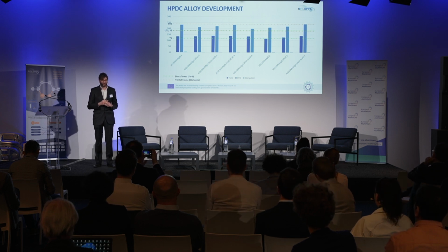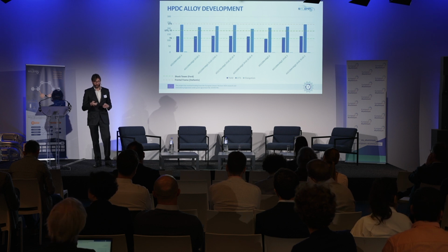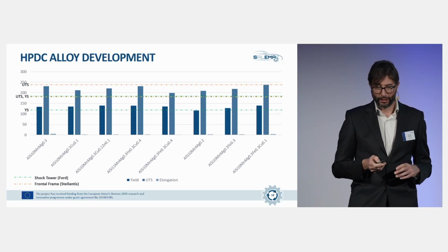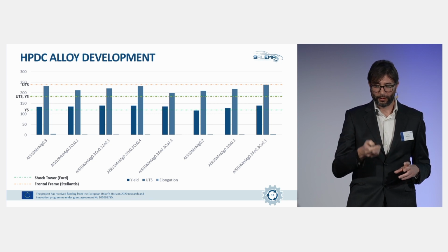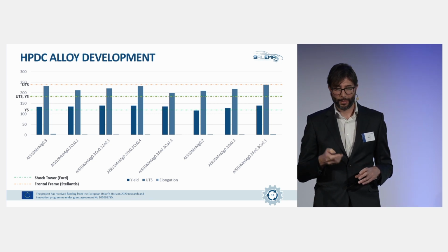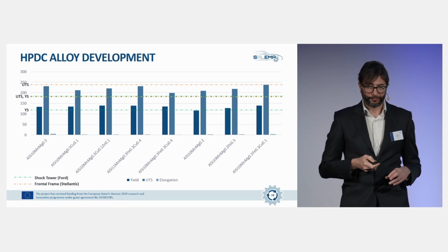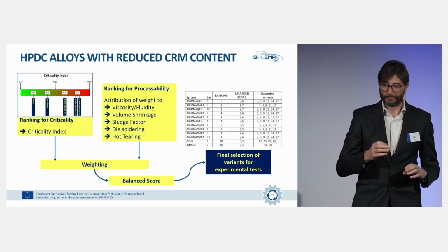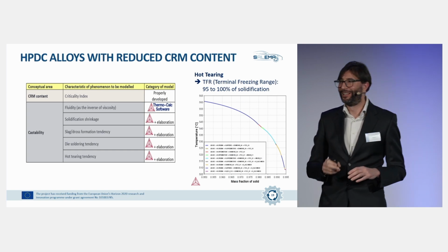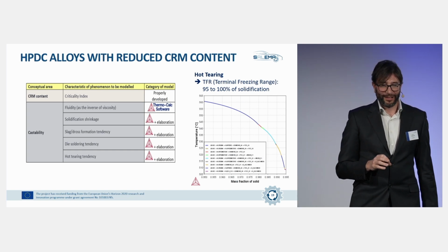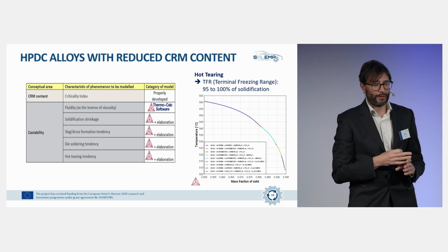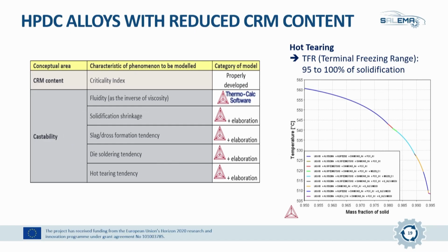With the other demonstrator, we had more trouble, but maybe after a heat treatment we could reach those requirements. And the biggest issue we had was with elongation, which without heat treatment was not reaching the minimum requirement. And then, one slide back, sorry. Then for alloy development, so we made,